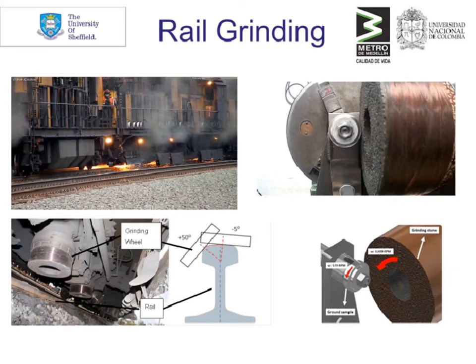We've been working on rail grinding for quite a long time now with Network Rail. That's been mainly focused at developing new grinding techniques. But we also have a collaboration with the National University in Colombia, where we're working at understanding conventional grinding a bit better and how this leads to white etching layer formation in rail in the high temperature pressure conditions that exist in the grinding stone contact. It's important to understand this because the white etching layer can lead to other forms of damaging accruing after grinding when the trains start to run over the track again. They can be crack initiation points, for example.